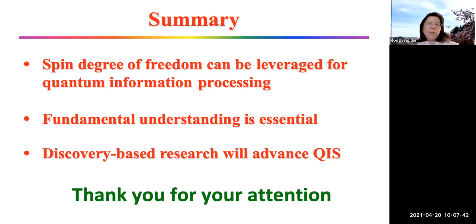We have probably, if it's not 10, 8 papers. We claim multiple. I did not bring it up because I don't want to belabor it here. What my lab does is quantum oscillation measurements, either de Haas-van Alphen type or Shubnikov-de Haas type. When you do that, you observe quantum oscillations, and then we plot this data, and they show geometric quantum oscillations.